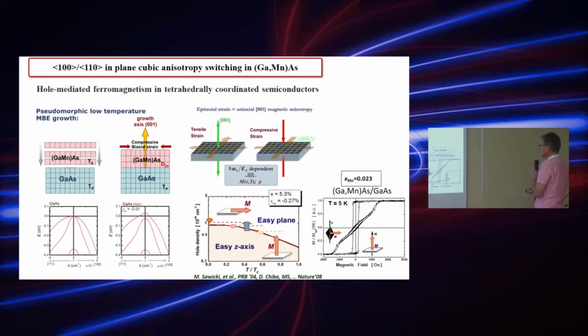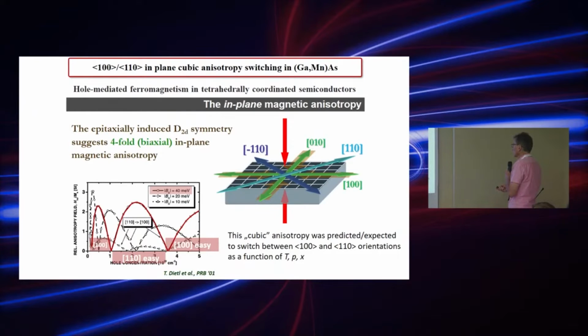in 2008. Just for the historical record, because for many people gallium manganese arsenide grown in the compressive strain case is regarded as an in-plane material. So this is tensile strained gallium manganese arsenide, and in this case perpendicular magnetic anisotropy is clearly observed. The magnetization curve measured with the magnetic field applied perpendicular to the layer has easy axis character, and for the same sample, under the same conditions, magnetization measured in plane has a sloping character, indicating the hard axis orientation.